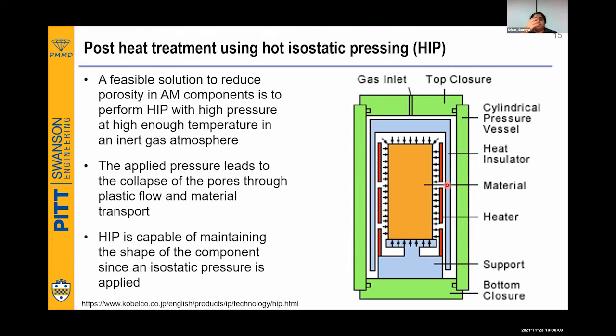So this hot isostatic pressing is a well-known process. Many of you might know it. The thing is, we will have a pressure vessel in which we keep our component, and there will be a heater, and the pressure is going to be applied isostatically, which means in all the directions we are going to give equal pressure, and we are going to use an inert gas atmosphere to avoid any oxidation or other related problems. So why we have to go for hot isostatic pressing is because, as I mentioned, we are going to do it at high pressure and high enough temperature in an inert gas atmosphere, and it is going to close the pores.